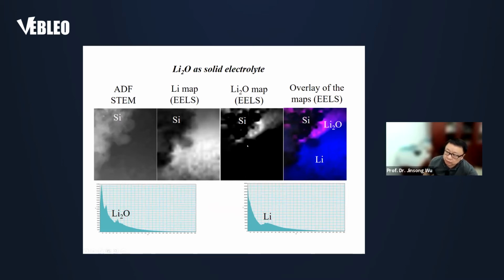So in order to demonstrate that we have lithium oxide as a solid electrolyte, we can identify the lithium oxide layer by using EELS. EELS is electron energy loss spectroscopy. And by using EELS, we can distinguish lithium oxide from metal lithium. By doing the EELS mapping, it is clear there is a thin layer of lithium oxide at the interface between the metal lithium and the silicon, which is the electrode material we use. So demonstrating that the lithium oxide is formed and it can be used as a solid electrolyte.